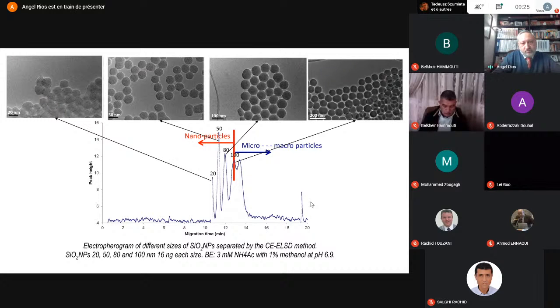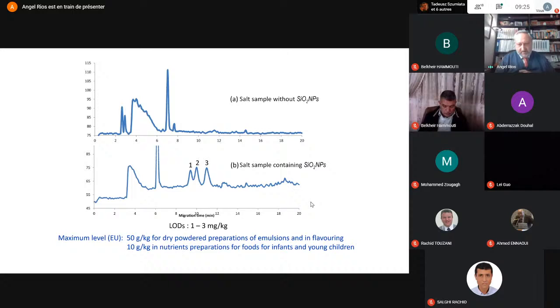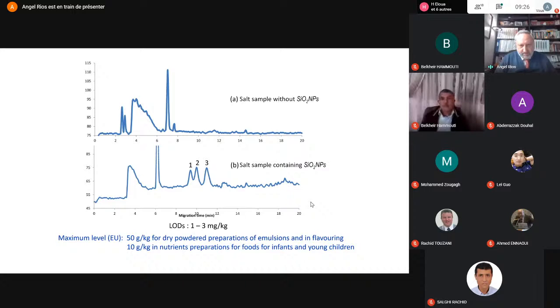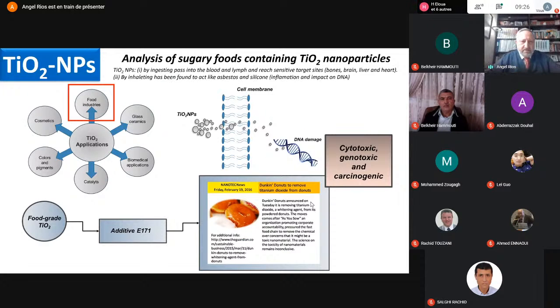But the objective is to check the presence or absence of silica nanoparticles in a sample, in this case, a salt sample. As you can see in the application, in the first recording at the top is the salt sample without these nanoparticles, and in the second case, the presence of silica nanoparticles in the second recording. It's important to say that the sensitivity of the method is adequate for the level of the legislation, for instance.